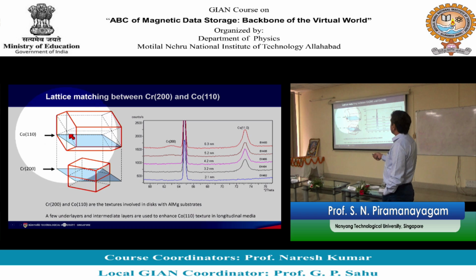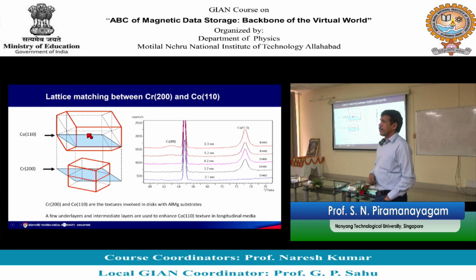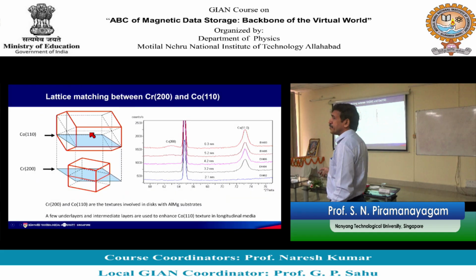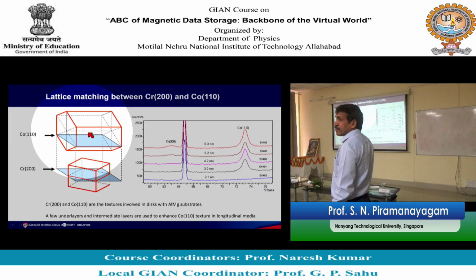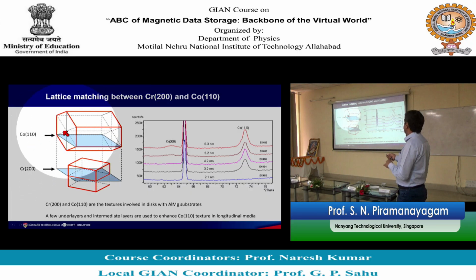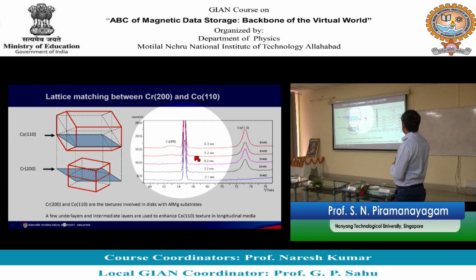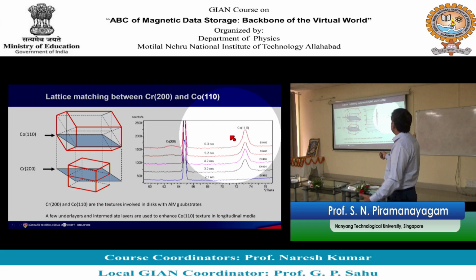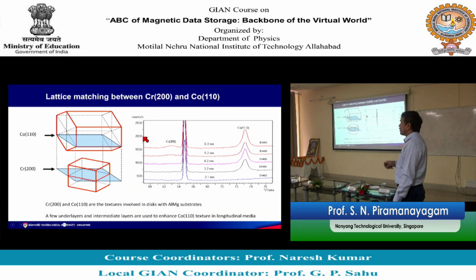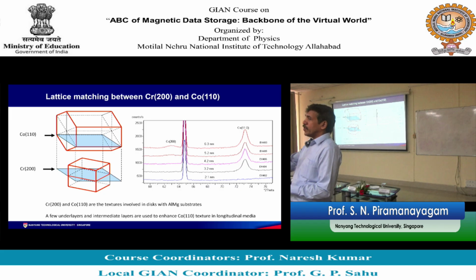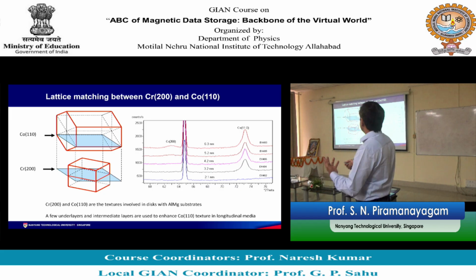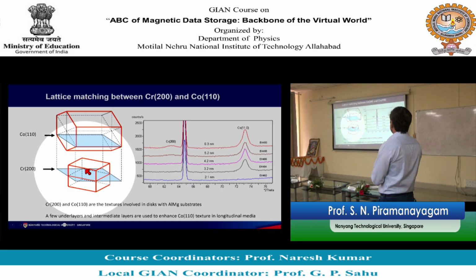Okay. So, where is the easy axis here? Where is the easy axis of magnetization in this picture? It is along the C axis, which is along this direction. So, this way we make the magnetization horizontal to the disk surface. You see, once you deposit some chromium, around 6.3 nanometer, you see a larger cobalt 110 peak, which means many of the cobalt grains are oriented parallel to the disk surface. So, this is one way to explain why we just do not use one layer for magnetic recording. We need some layers to keep the magnetization in plane and so on.